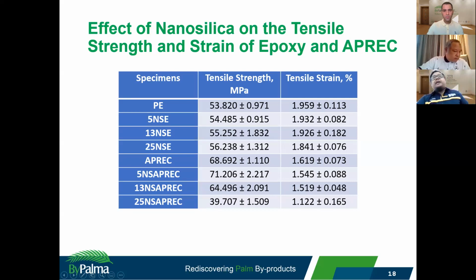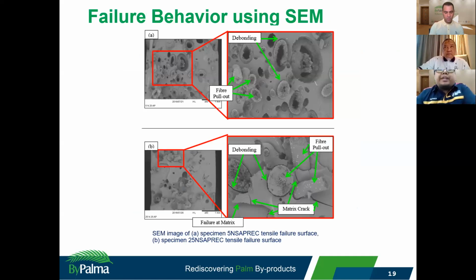Actually, this occurred because of improper wetting, which is shown here. We can see the electron microscopy image for the 5 nanosilica APREC specimen at the top, and for 25 nanosilica APREC at the bottom, B. From the previous slide, the addition of 13 and 25 reduced the properties. This reduction in tensile properties occurred due to the high content of Arenga Pinnata and nanosilica inside the composite, which caused the epoxy resin to be unable to perfectly coat the Arenga Pinnata fiber. This phenomenon we call improper wetting.